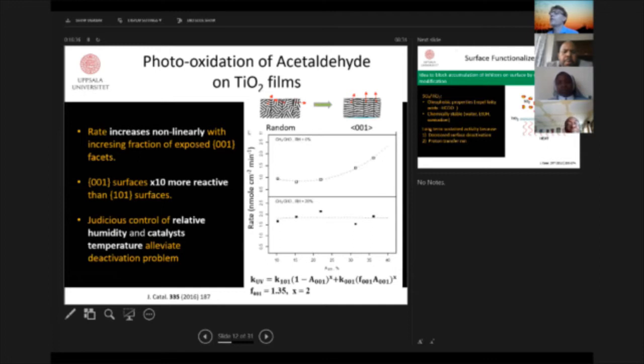And we can understand this, from the random to the oriented phase, by analyzing details of these surface reactions. A conclusion, apart from the quantitative numbers listed here, is that you can control the relative humidity and the catalyst temperature, and of course also the surface texture, to optimize the activity.